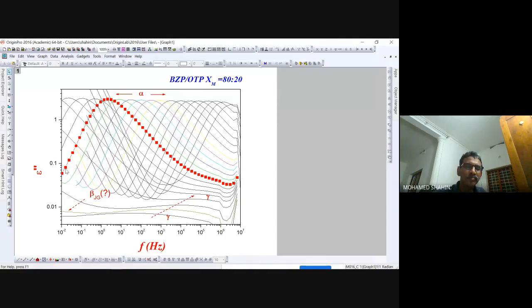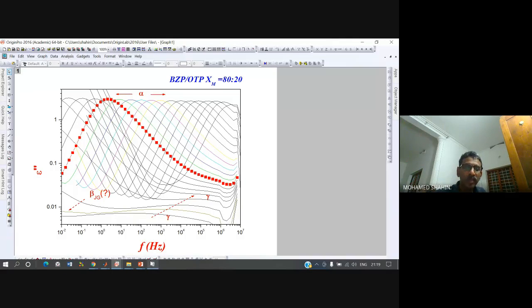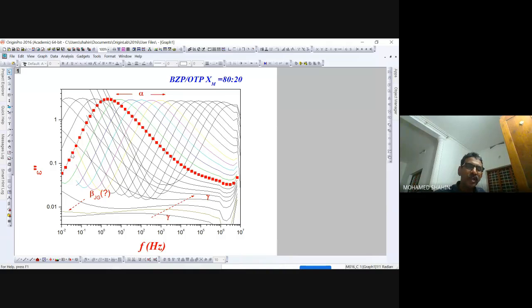Okay. Now there are certain cases. I have observed that when your signal is very poor, and you are taking data here, you are only taking 1 period. In that case, in certain cases you need to take 2 periods so that it averages out the noise, and in certain other cases I have taken 3 periods.